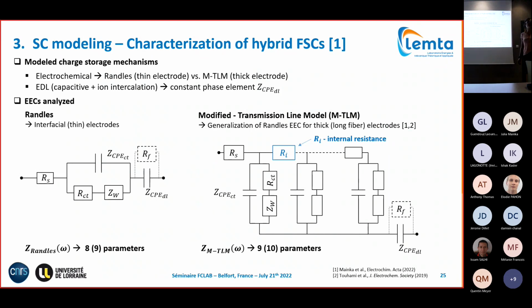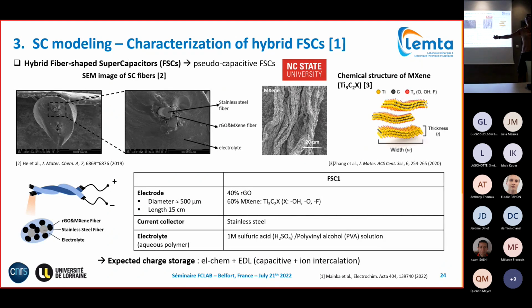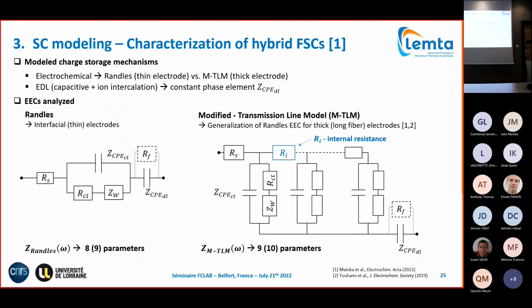The classical Randles circuit that I just introduced before, but the Randles circuit, as I said, is based on the hypothesis of interfacial electrodes, and even more so if you have fibers, long fibers, with thick electrodes. So what we developed is a kind of modified TLM, inspired by what we used for PEMFC characterization, meaning it is a transmission line model composed of individual Randles circuits that are distributed along the fiber length and separated by what we call internal electric resistance. For the moment I leave it open whether it is linked to ion transport or electron transport.